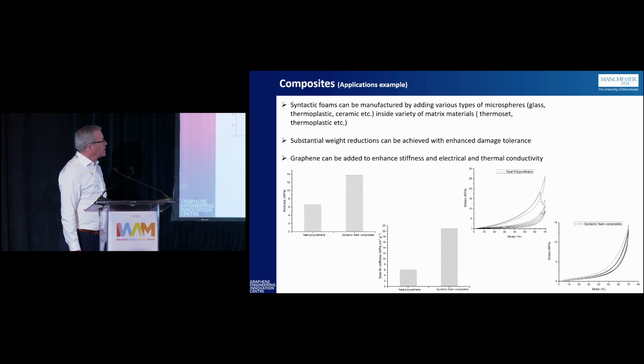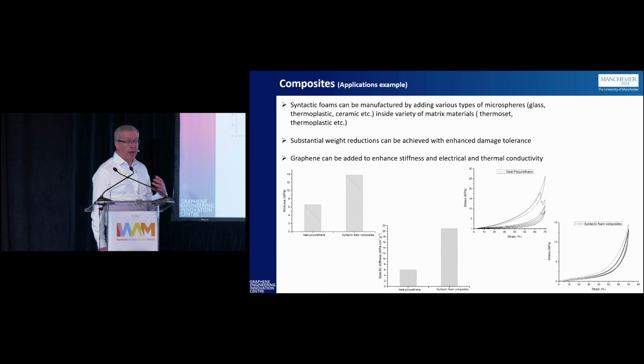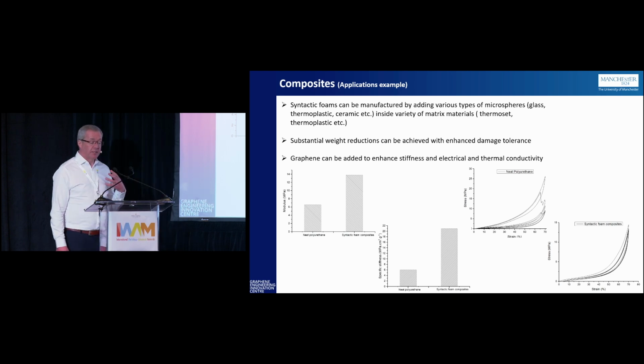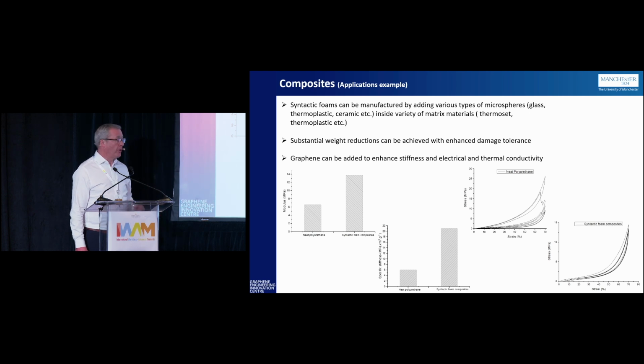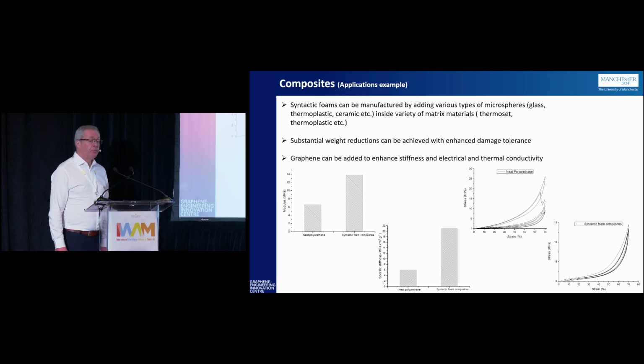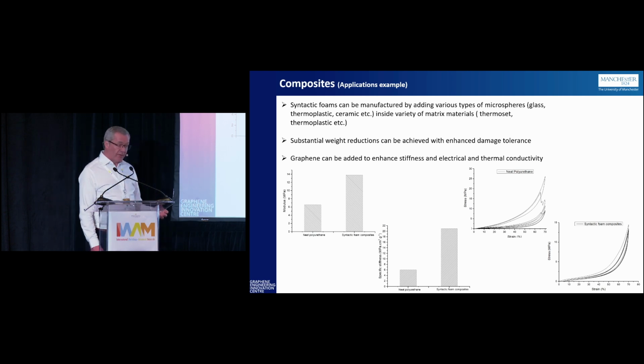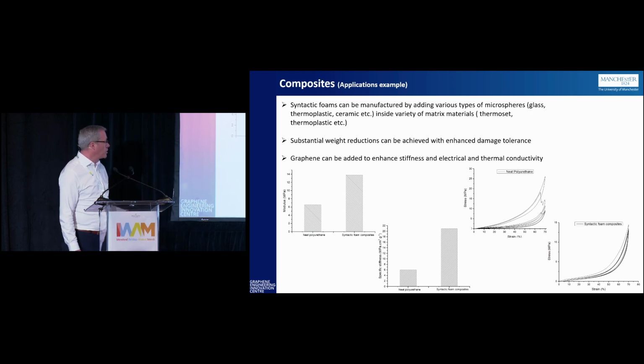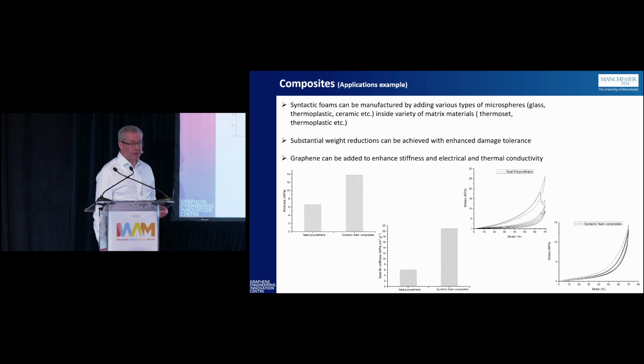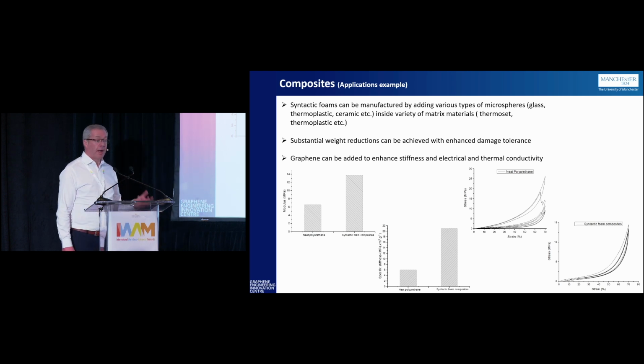Syntactic foams is another area, which is then the lightweighting of foam. So this is the taking out of the volume of the foam and using fillers. Graphene in those fillers and other 2D materials can be used to actually substitute the strength losses. And we can demonstrate that from the neat polyurethane foams, we can get significant increases in compressive and tensile strength just by adding those systems. And it's all about that kind of formulation and optimization.